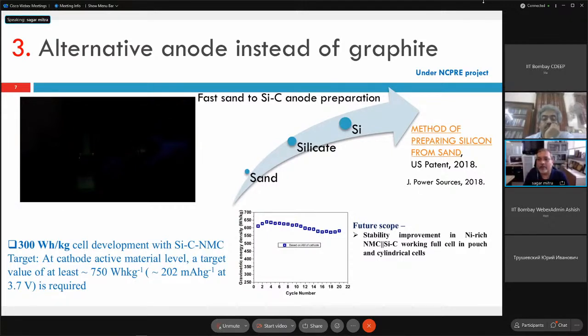Silicon is one of the components people are looking at, because silicon can store lithium 10 times more than graphite can. If graphite is 300 ampere hour per kg, silicon can make 3000 ampere hour per kg. So that much energy can be stored if I use silicon instead of carbon. But there are a lot of problems.